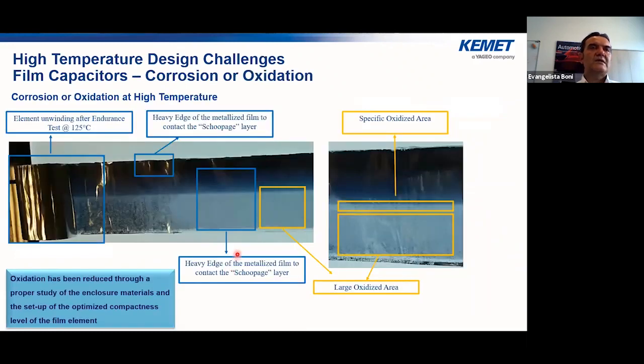Here we can see the most important part, showing how the standard series can fail at high working temperature. It was possible to see how a virgin film looks. And here we can see a capacitor that has been unwound after an endurance test performed at 125 degrees on a standard capacitor.